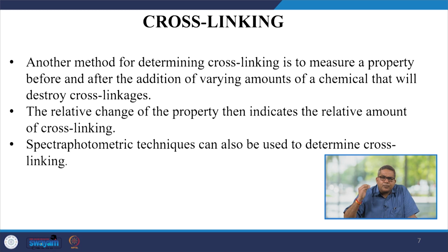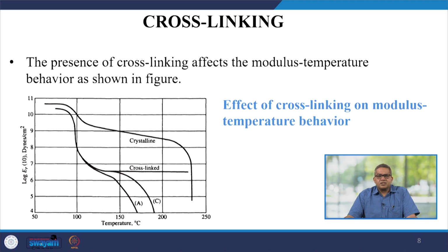One method is to measure a property before and after addition of varying amounts of a chemical that will destroy the cross-linkage, so that it can break this network, and then determine the relative change of property. This indicates the relative amount of cross-linking. Some spectrophotometric techniques are also available to determine the cross-linking aspects. Now, here you see that different types of cross-linking affect the modulus versus temperature. Here, the temperature versus modulus for the crystalline cross-linking, different types of effects are discussed in this particular plot.